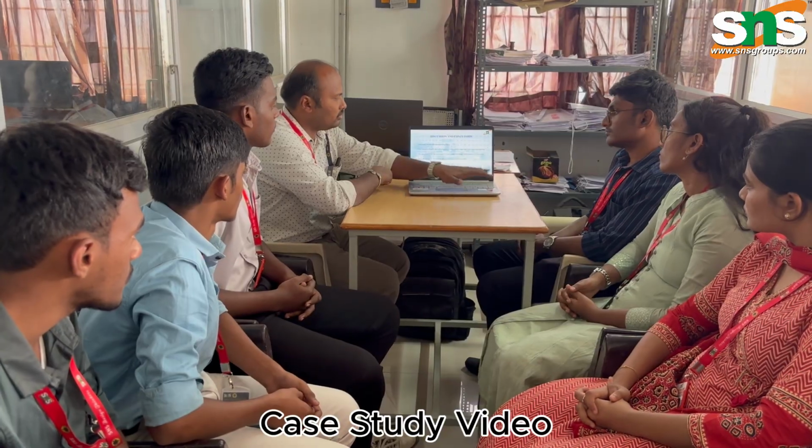Finally, coming to the conclusion, we concluded that the shaft broke because of rotating bending fatigue. For the grade AISI 4340, the optimum fatigue resistance will be at 45 HRC, which would provide the fatigue endurance limit.